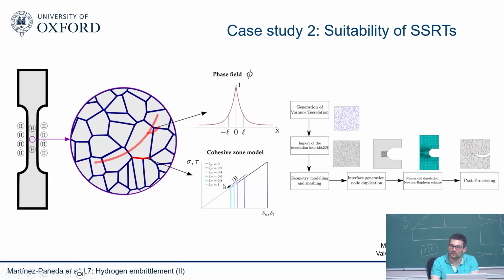Because in this material, in other materials, how hydrogen interacts with the failure process is still very much under debate. But in these nickel superalloys, it's very clear, you get intergranular cracks. So then they said, okay, we put hydrogen there. The cohesive strength is degraded with the hydrogen concentration. We have a traction separation law, it's degraded with concentration. And then the phase field just tells me whether I have ductile fracture. So then I have both things competing at the same time. And then I just run it and see which one happens first, whether ductile fracture or brittle failure.